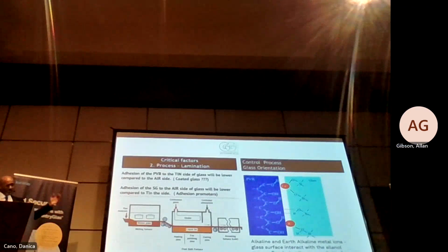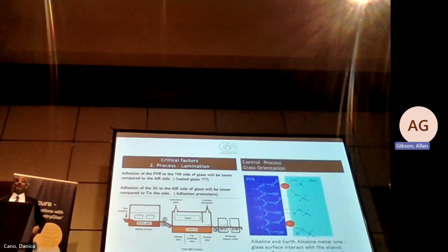Why are we saying air side and tin side? The moment you have alkaline or alkaline earth metal ions on your glass, it will create an interaction. It will create a problem for your adhesion, and this cannot be avoided. In the Middle East today, everyone wants outside-coated laminated glass. You cannot have air side to air side on a PVB on a coated laminated glass, because coated glass has one side which has coating and it is the air side. So the only side left for you to laminate is the tin side.